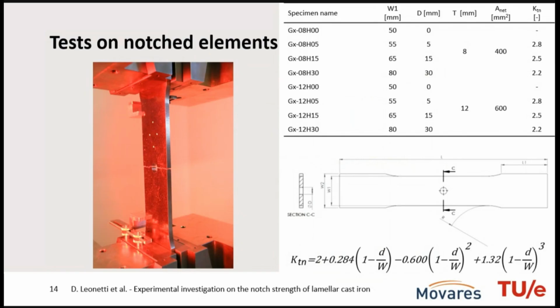Together with this, we had a test series of larger specimens as compared to the coupon test without a hole, because we wanted to see, and that's something I will briefly mention later, whether the size of the specimen could bring in a higher chance of having defects here and there. So whether with larger specimens there were more specimens that we had to reject from the analysis because of the presence of defects.